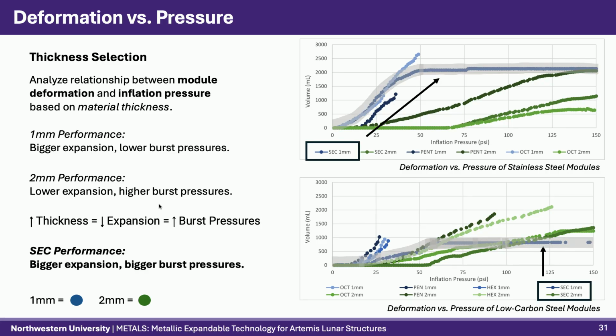Notably, the SEC geometry remained unchanged by thickness. As evidenced by the figure to the right, this geometry demonstrated initial deformation rates, just like 1mm thick modules, but survived pressures higher than 125 psi, like 2mm thick ones.